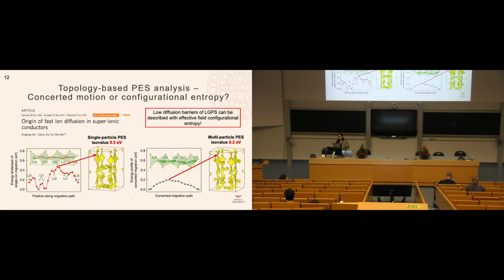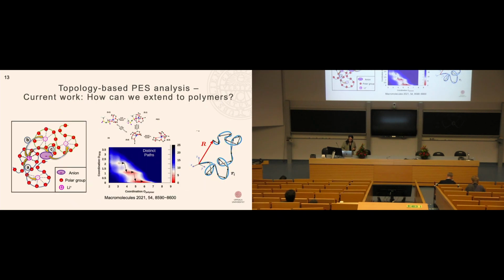While these two different viewpoints of the configurational entropy and the concerted motion might not necessarily contradict each other, it does indicate that we actually don't need to explicitly consider these simultaneous transitions. But this is also reproduced by the average mean field of the configurational entropy of the interacting particles.